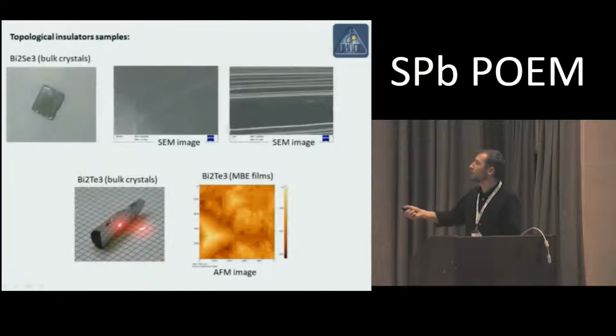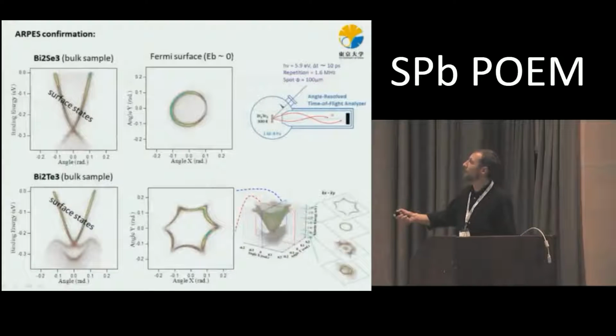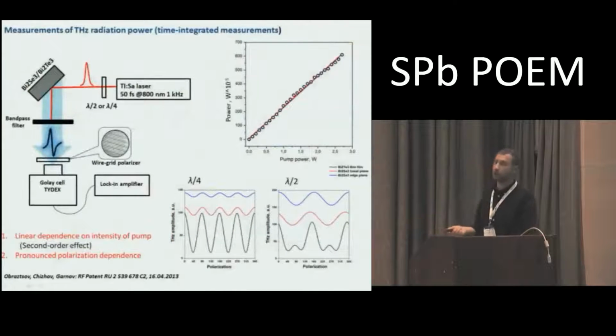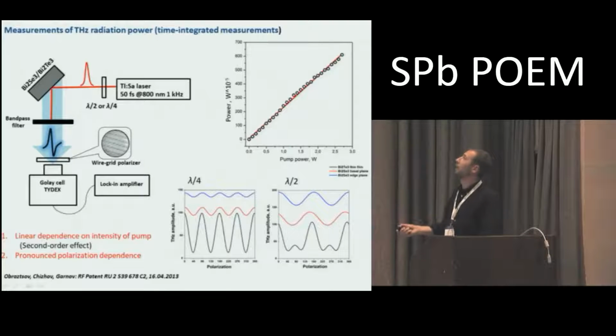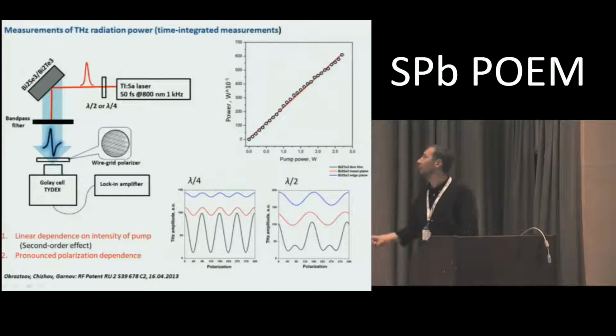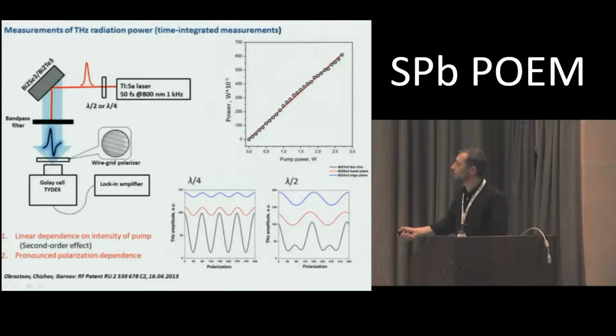But in our experiments, we employed different samples of topological insulators, namely bismuth selenide and bismuth telluride crystals. Their surface states were confirmed by ARPES measurements. So here, nice Dirac cones can be clearly seen. And so we employed terahertz emission spectroscopy. First, we measured the power. We performed the time-integrated measurement just by using a Golay cell and obtained the dependence on both helicity of light and rotation of linear polarization.